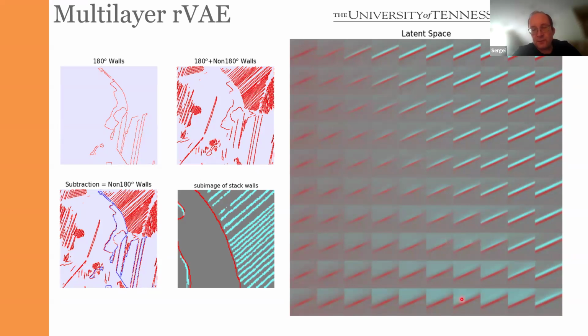What happens in this part, you can see that the red line is visible, but the blue line is kind of more diffuse. What it means is that we are in this type of region where the red domain wall is pinned on multiple blue domain walls, but we don't have enough representation power in order to resolve where they are. And this is the most interesting part.